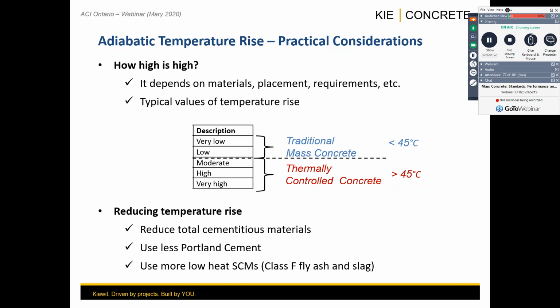So as you're evaluating the mixes, if you see a mix that you're going to use in traditional mass concrete that has too much heat, most likely you want to start looking at what to do, because it's not necessarily the best thing you can do for a traditional mass concrete placement. You want to optimize that mix. Reducing temperature rise means reducing total cementitious, using less Portland cement and using more fly ash and slags or low heat cementitious materials.